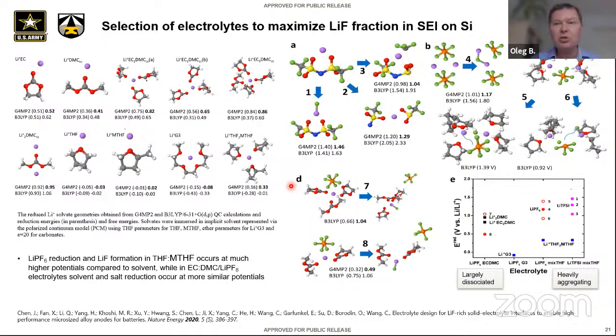And they have shown that that's indeed the case. So the question was, what is the best electrolyte to try to generate almost pure LiF, or as pure as we can? In order to do that, we can do screening and specifically calculate the lithium EC and DMC reduction potentials. There is a slight preference for the EC, to be about 0.5.